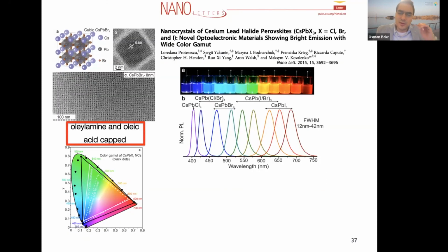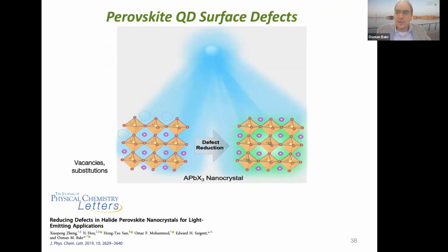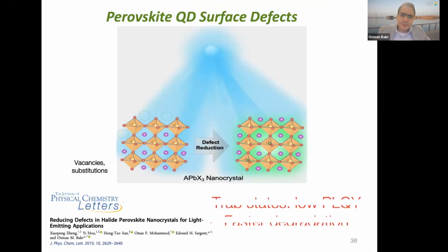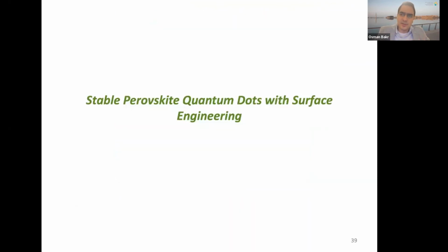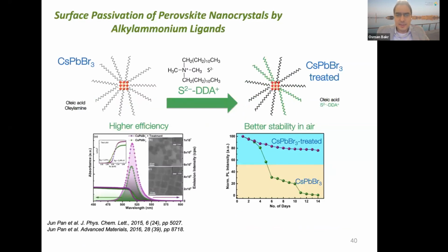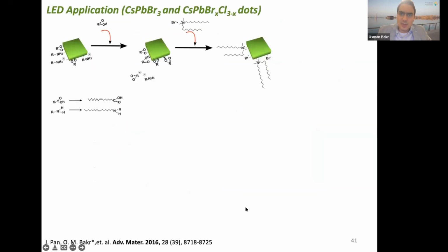The problem is the material is unstable, and so you need to find different capping ligands than the ones that are normally used to stabilize the material. So we started looking at ways of reducing defects and how to prevent the nanocrystals from degrading, and that's what led us to developing surface engineering methods for perovskites. One of these methods was exchanging the ligands on the surface with alkyl ammonium ligands. That allowed us to mitigate surface acid-base reactions that degrade the surface and obtain a very stable nanocrystalline compound.